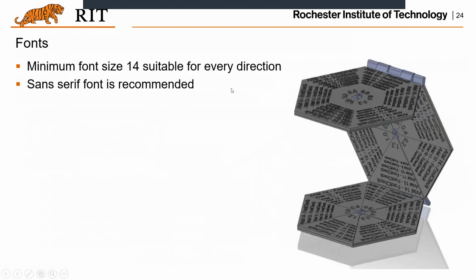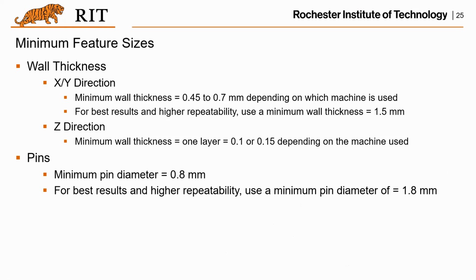Here shows the fonts. Basically, these are the letters, all the words, that can be added onto the prints. And there are different fonts for different printers. Some of the minimum feature size, the wall thickness in X, Y and Z. As you can see here, in the XY minimal wall thickness is 0.45 to 0.7 millimeter. And in this direction, the wall thickness for one layer is 0.1 or 0.15, depends on the machine, depends on the different system you're using.